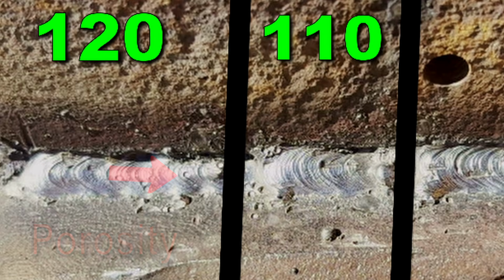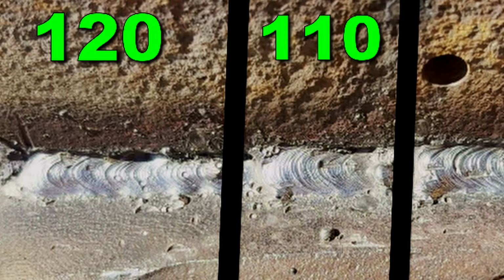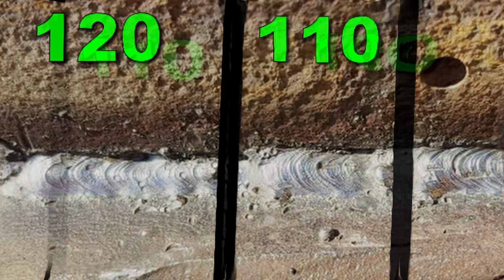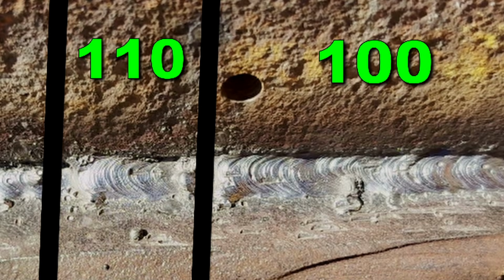Now moving on to our 110 amp weld, you can see there's almost no spatter and the undercut is much smaller. And for the 100 amp weld, it looks like we finally got it dialed into a range that's not too volatile. There's no deep undercut, there's no spatter. There is this blob where I pulled the rod away for a second, and you can see these narrow pointy beads. These beads are a telltale sign that I was moving too quickly.